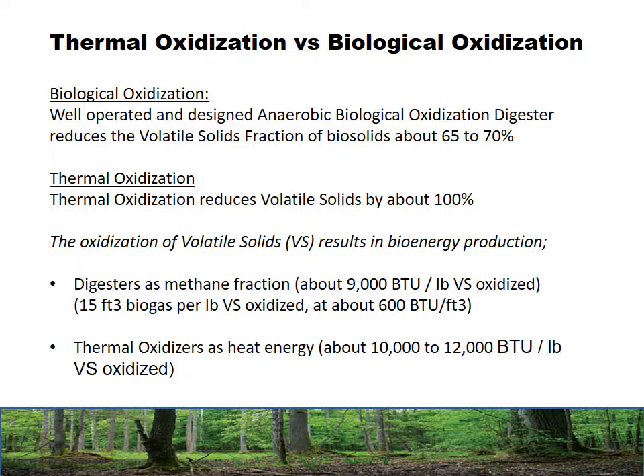So in terms of bioenergy production, when you look at digesters, the methane fraction is about 60% and has a heating value, a calorific value, of about 600 BTUs per cubic foot. You make about 15 to 16 cubic feet per pound destroyed. That results in about 9,000 BTUs of energy per pound of volatiles destroyed. In a thermal oxidizer, you produce heat energy of about 10 to 12,000 BTUs per pound destroyed. By the way, there's a lot of information on co-digestion. There's co-incineration too. The addition of fats, oils, and grease only increases these kinds of numbers. You can use food waste and the same volatiles that you can use in co-digestion in co-incineration.